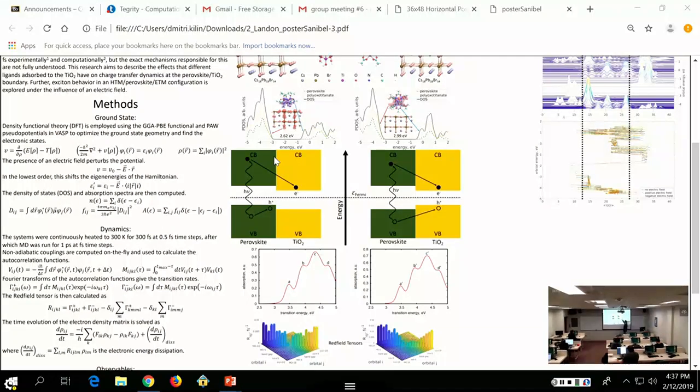In the acetate model, however, you end up with both of the band edges being localized on the titanium dioxide. And so if you do get a charge transfer, it's likely to be very short-lived, not preferable for extracting those charges, because both of the photoexcited charges are likely to land in the titanium dioxide, just exciting that one species energetically.